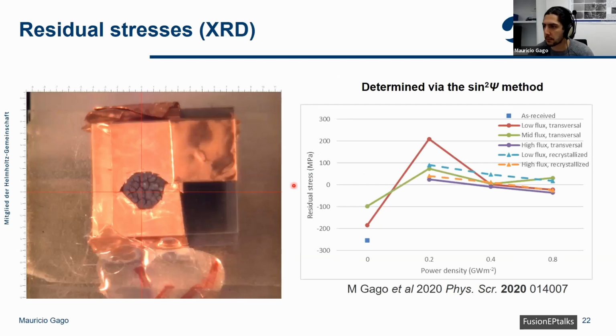So as I mentioned at the beginning, we saw that for some samples, especially at lower power loads, the transversal samples have a higher cracking threshold than the recrystallized samples. This has also been seen in previous tests, and so here we tested via X-ray diffraction and with the sin squared psi method the residual stresses in the samples, especially in the laser spot.